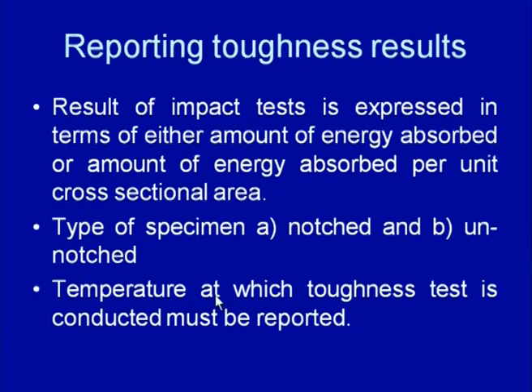Thereafter, it is also mentioned what type of specimen was used, whether it was a notched or unnotched specimen, or the temperature at which the toughness test was conducted, because the temperature of the material significantly affects its toughness value. Therefore, it is important to mention the amount of energy absorbed, the type of specimen used, whether it was notched or unnotched, the temperature at which the test was conducted, and which method of test was used, whether it was IZOD or the